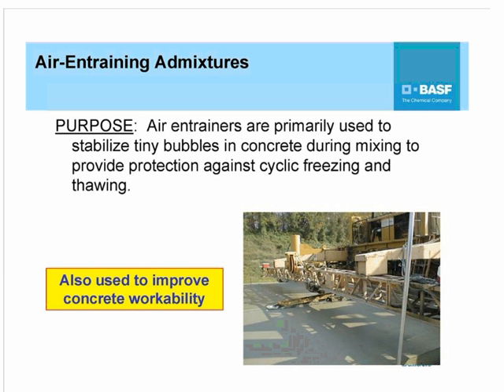Now, as a result of that, air entraining admixtures or entrainers are typically used in concrete, and the primary purpose is to basically stabilize tiny bubbles in the concrete that are formed during the mixing process, and by so doing, provide protection to the concrete against cyclic freezing and thawing under saturated conditions. Now, it turns out entraining admixtures also help improve the workability of concrete because of the ball-bearing effect that they